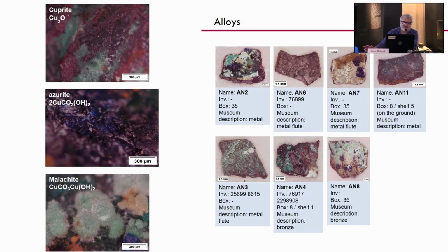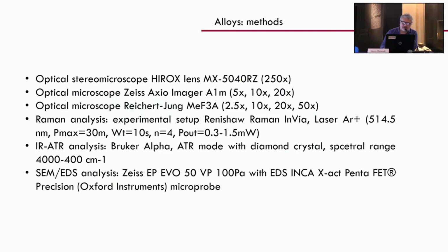And as you can see, the first analysis that we performed was to understand the degradation process, the oxidation process of the alloys. So we got different materials, as you can see, cuprite or azurite or malachite, that are typical of the alloys and the degradation process of this kind of materials. We analyzed all the samples, but I just show you some of them because of the time. And we used different instrumentation to analyze them. And of course, we try to understand the original alloy and all the characteristics of those kind of materials.